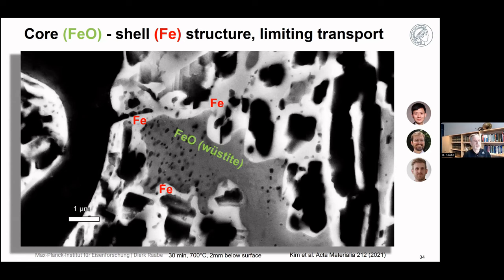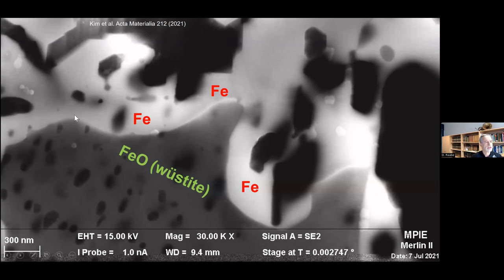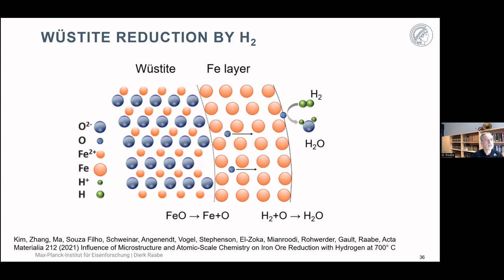When we zoom a little bit more in, then you see that dense iron layer around that Wüstite. And you see, of course, all the Swiss cheese porosity in the center where the oxygen has been removed and collapsed. The free volume has collapsed into this nanoporosity. But you can also understand that you need to transport the oxygen for this reduction through that very dense iron layer. And that is a very, very slow transport mechanism, which explains to some extent why this overall kinetics is so sluggish.